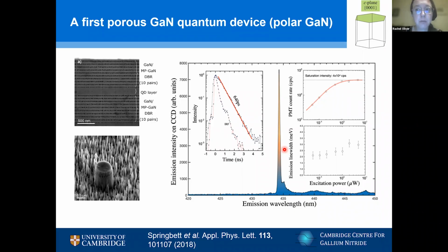When we have tried intentionally doping the quantum dots, we've found that it basically kills the luminescence. We're not quite sure why. You don't see good dot luminescence in the highly doped structures at all. For quantum wells, you can certainly use high doping to shield the fields to a greater or lesser extent. In quantum dots, we have yet to make it work. Something's going on, either affecting the growth of the quantum dot in the morphological sense, or affecting the states in the quantum dot and preventing the single photon emission that we're looking for.